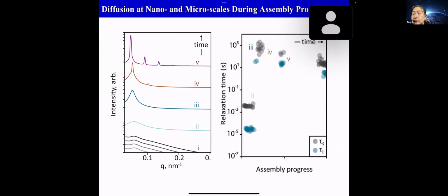And we also look at the tau L in the larger scale. We wanted to see nanoscopic arrangement versus microscopic, because we're dealing with nanostructure and microstructure together. We want to see when the system begins to couple versus when it's completely separate. As expected, before stage 2, that's where you begin to see this correlation hole in there. And the system has a really high mobility. That is consistent because your nanostructure hasn't really formed.